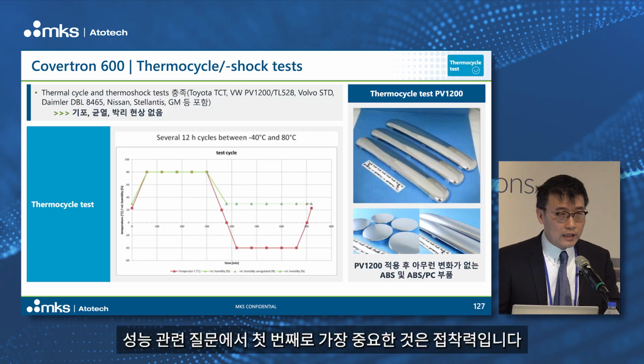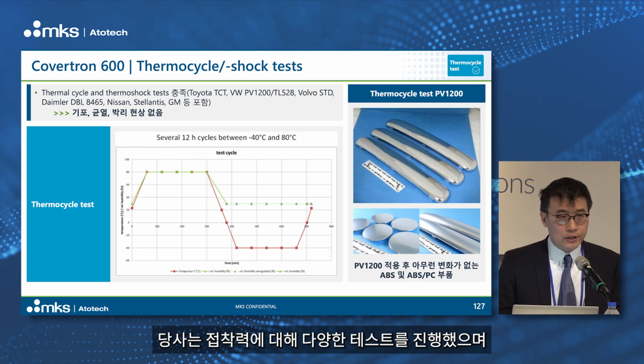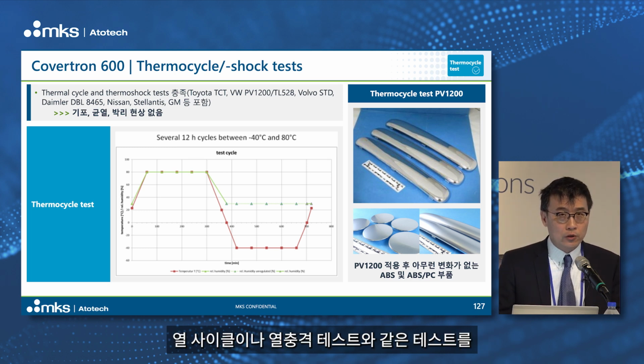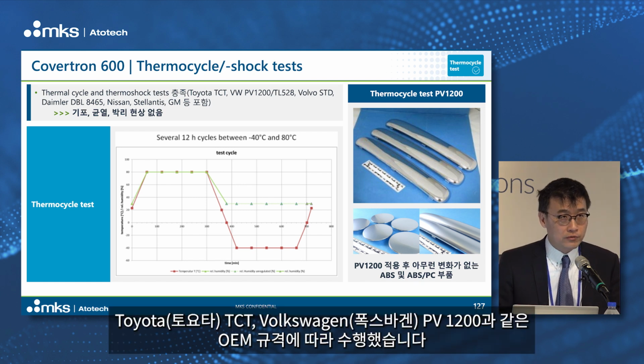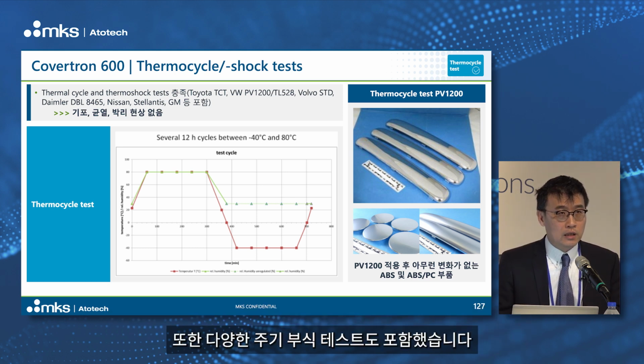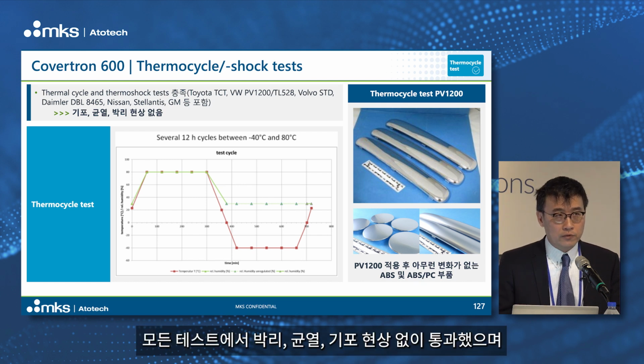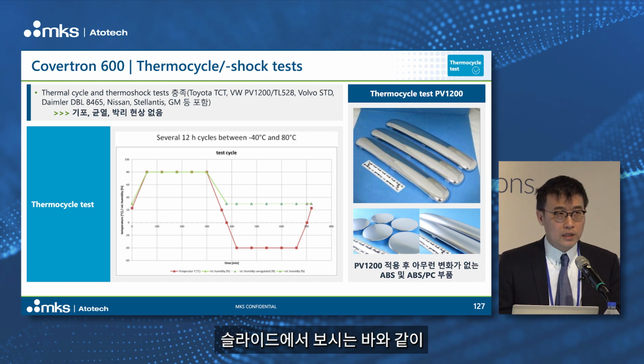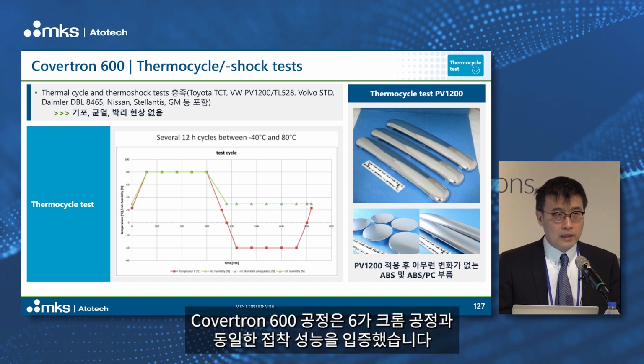The first question that you will ask about the performance is about adhesion. We did a lot of tests on adhesion, like different thermal cycle or thermal shock tests according to different OEM specifications, like Toyota TCT, Volkswagen PV1200, and different cyclic corrosion tests. We passed those without delamination, without cracks, without blistering. You can see all of this in our slides here, and it's proven that the adhesion is almost exactly the same, as good as the Chrome 6 application.